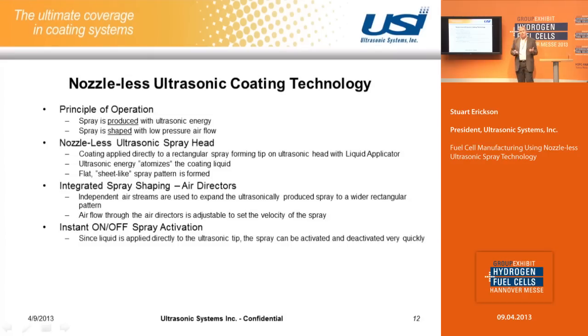So a little bit more detail about the principle of operation. We produce the spray with ultrasonic energy, and we shape the spray with low pressure air or gas flow. The ultrasonic head has a vibrating tip, and the coating is applied directly to that vibrating tip, and the ultrasonic energy breaks the liquid up into a fine spray, and it comes off in a flat pattern, almost like a sheet or a waterfall. And then the air directors will expand that spray pattern and maintain the rectangular shape, but just make it wider.